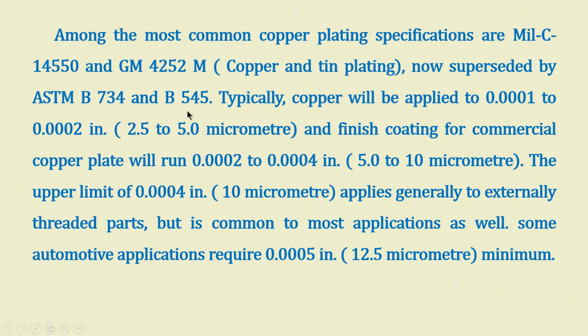0.0001 to 0.0002 inches, that corresponds to approximately 2.5 to 5 micrometers, and the finish coating for commercial copper plating will be approximately 0.0002 to 0.0004 inches. That corresponds to 5 to 10 micrometers, that should be more than enough. The upper limit is 0.0004, that is 10 micrometers.